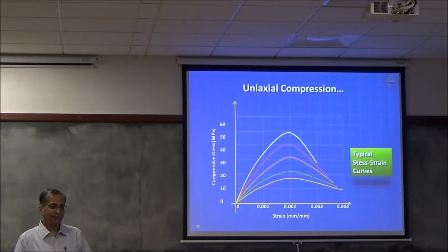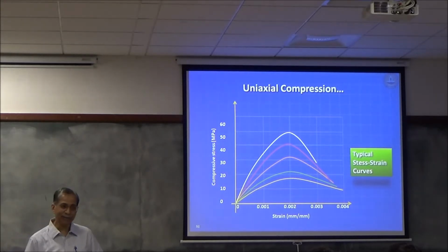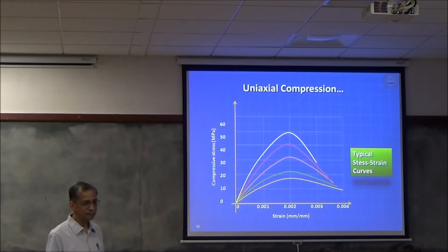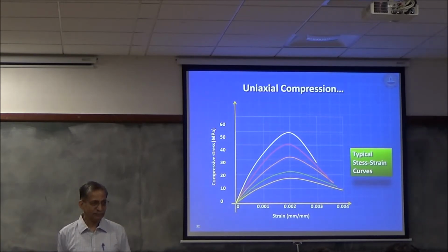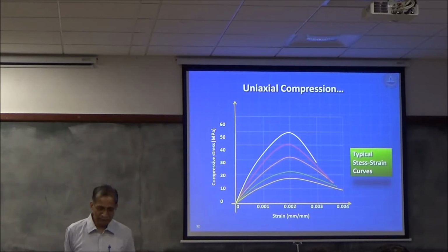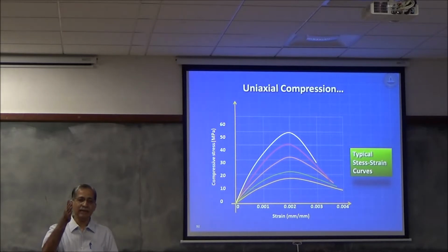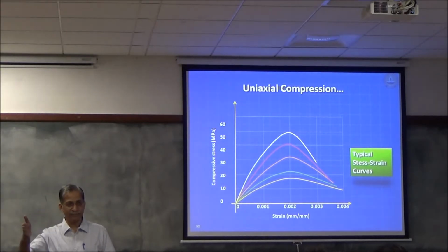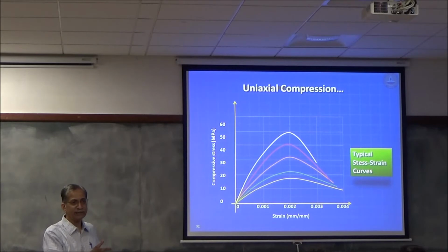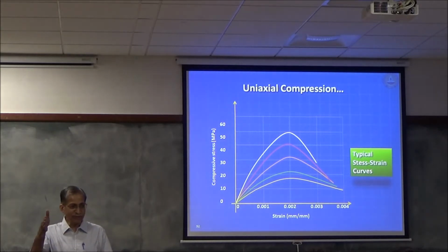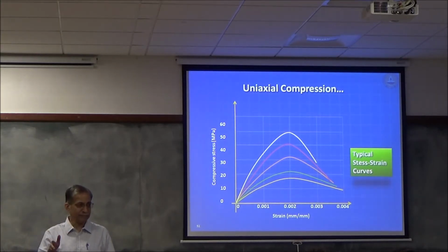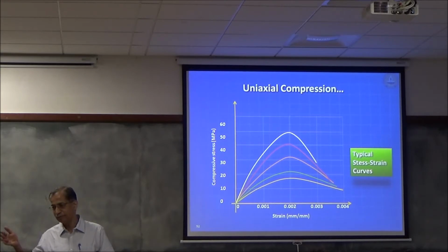How to verify that it's the same? If you had to do an experiment, what would you do? How would you do it? In fact, probably you have to do it in your lab. People have done a lot of studies on this. So you can create small column-like systems where you can apply an eccentric load. So first you make it concentric, you get pure axial compression. Then you slowly shift it so that you have compression with bending, just like you have in a beam.